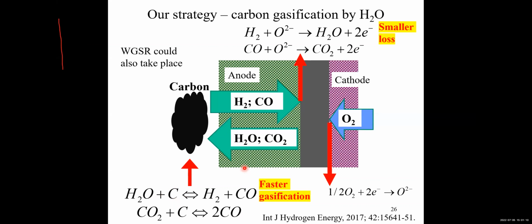Then we did some theoretical analysis, and we find there could be two benefits using water for carbon gasification. First one is the carbon gasification by water can be much faster than carbon gasification by CO2. Second, using water for carbon gasification, we will not only produce carbon monoxide, we will also produce hydrogen. So both hydrogen and the carbon monoxide can participate in the electrochemical reaction for power generation. Hydrogen oxidation is much easier than carbon monoxide oxidation, meaning this reaction gives much lower polarization resistance. So using water for carbon gasification, we have two benefits: faster carbon gasification, and reduced activation overpotential, where the polarization resistance can be greatly reduced.